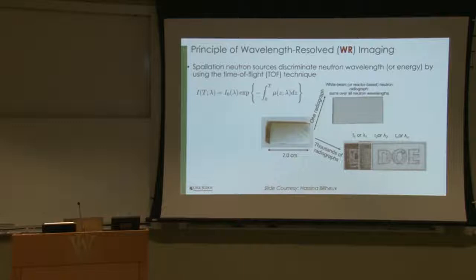Now the reason this kind of contrast difference happens is because this material is crystalline, right? And you get scattering from these points. So that's the benefit of using time of flight neutrons. But there are challenges in using this technique to do CT or tomography.